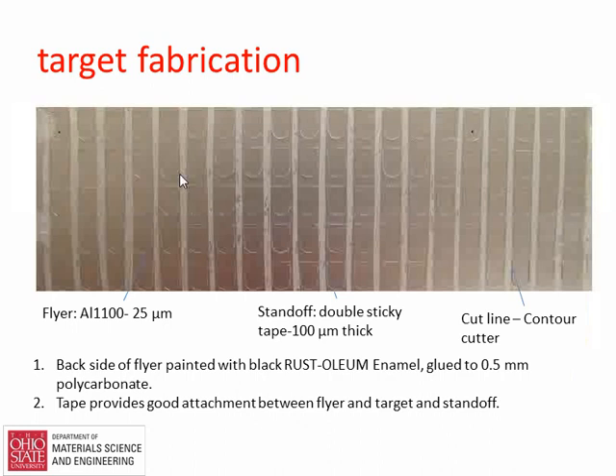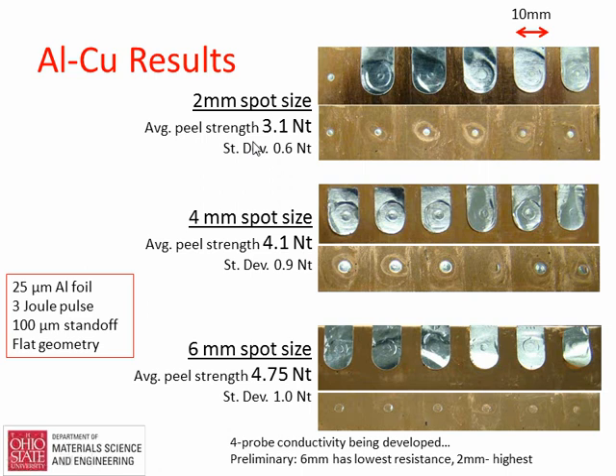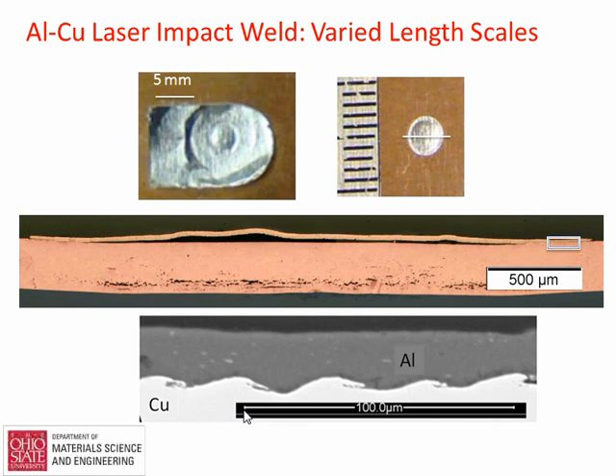At 2 millimeter spot size, really high power density, she got welding through all of these. At 4 millimeter spot size, upon peeling, she saw that there was no welding or weak welding in some of the cases, whereas with 6 millimeter spot size, it was even weaker. The welds tend to be in the form of a perimeter instead of a spot, and that's again because